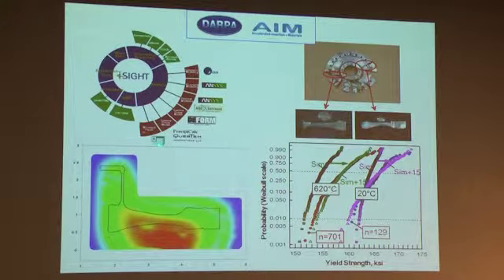We also had to calibrate and validate structure-property models implemented as analytical functions in a spreadsheet. PrecipiCalc was the key new numerical simulator needed to enable this technology. After calibrating against existing turbine discs, a demonstration project designed a subscale turbine disc using these tools and tested it to overspin failure to validate performance predictions. This also gave us the opportunity to section companion forgings and validate the predicted spatial variation in microstructure and properties, where we were able to predict that spatial variation well within part-to-part variation.